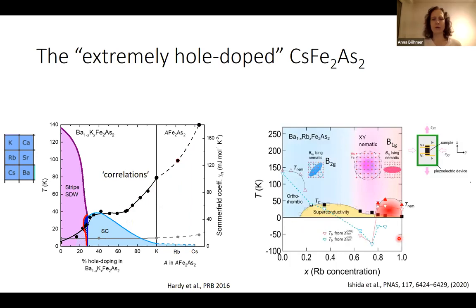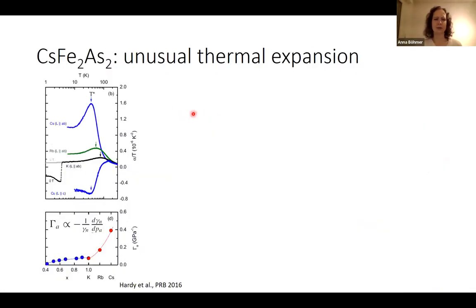There has been a recent report about nematicity in these compounds, going from the barium directly to the rubidium one. And what was reported is a flip, a change from a B2G-type nematic behavior to a B1G-type nematic behavior. So a flip of the nematic directions, deduced from elastoresistance measurements. We wanted to start with the most extreme compound, the cesium-122 here. And there is another interesting property of this. It has not only a huge Sommerfeld coefficient, it also has a huge Grüneisen ratio of the Sommerfeld coefficient.